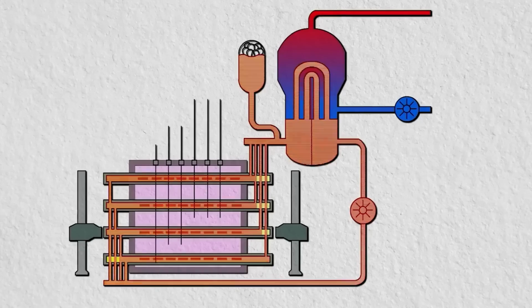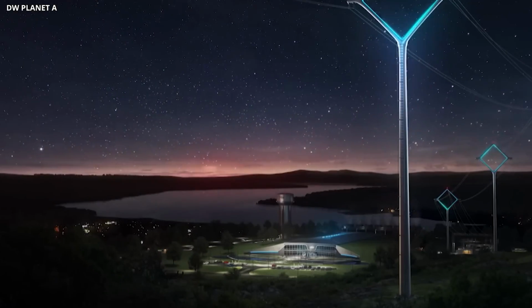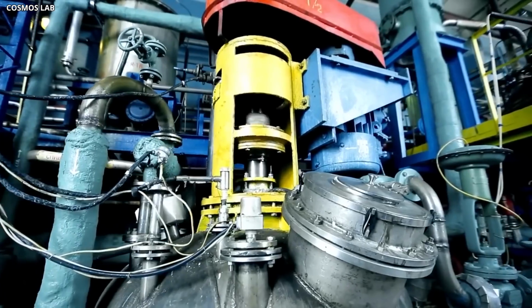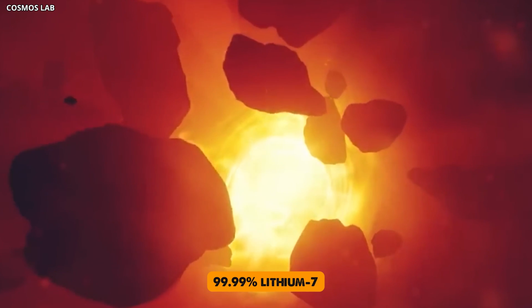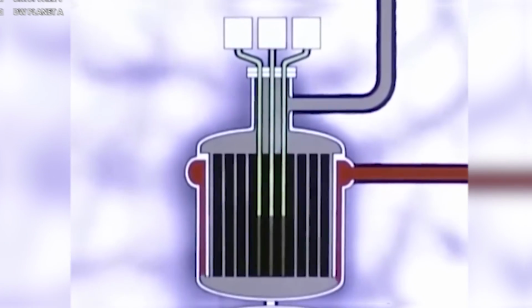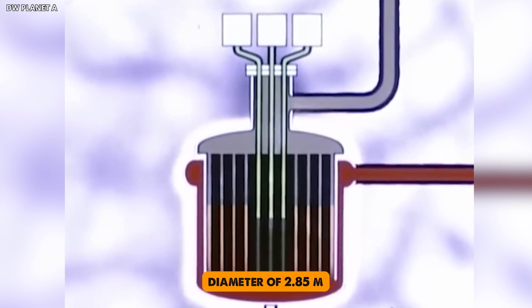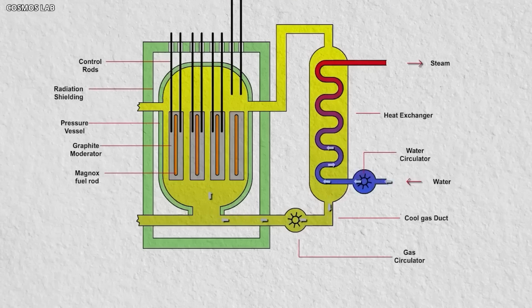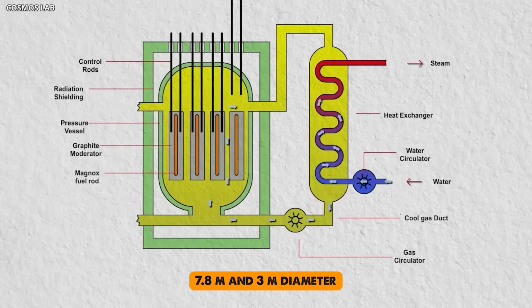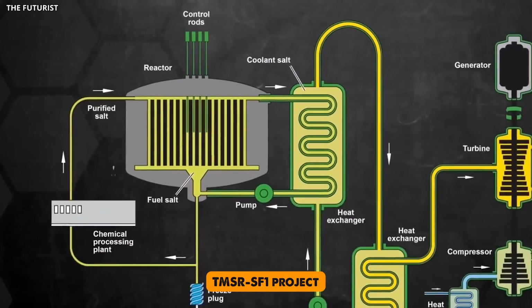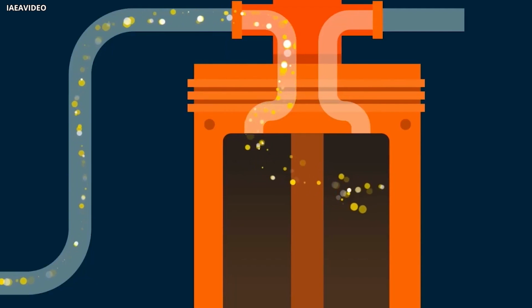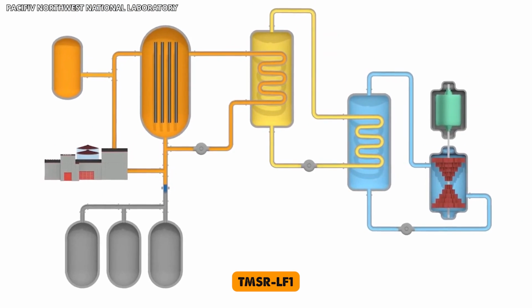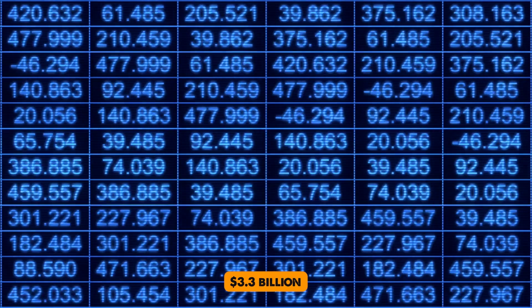TMSR-SF1, containing 17% TRISO fuel. This fuel is the same one used in high-temperature gas-cooled reactors. The reactor operates at low pressure with a primary coolant of lithium beryllium fluoride that is 99.99% lithium-7 and a secondary coolant of FLiNaK. The core of this reactor is 3 meters tall with a diameter of 2.85 meters, all housed in a pressure vessel that stands 7.8 meters high and 3 meters in diameter. Residual heat removal in this system is achieved passively through cavity cooling. While the TMSR-SF1 project predicted an operational life of 20 years, it has been discontinued since. Meanwhile, construction is underway on the 2-megawatt thermal TMSR-LF1 reactor at Wuwei in Gansu, part of a $3.3 billion program.